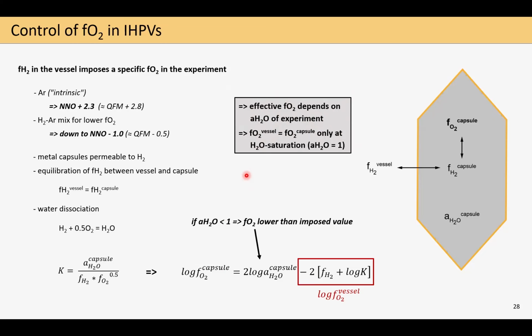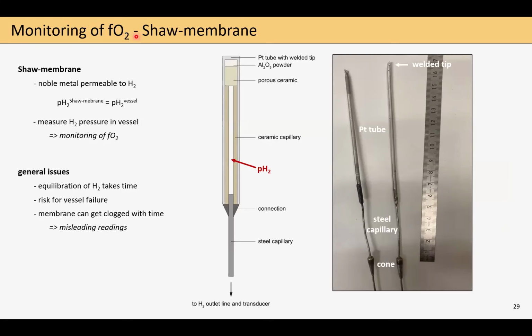And this is a very important principle and also applies to many other fO2 buffering techniques we're currently using in experimental petrology. So this is how the buffering works, but how can we now monitor if we added the right amount of hydrogen to reach the fO2 conditions we wanted? Well, one first possibility for this is the usage of so-called Shaw membranes, where you see here the general setup of how they are built, or here some images of them in reality. And in terms of functioning, they are based on exactly the same principle as the fO2 buffering before, where the noble metals are permeable to hydrogen, meaning that the partial pressure of hydrogen we can measure inside of the Shaw membrane via the connected transducer at the outside of the vessel will equilibrate with the hydrogen partial pressure inside of the vessel.